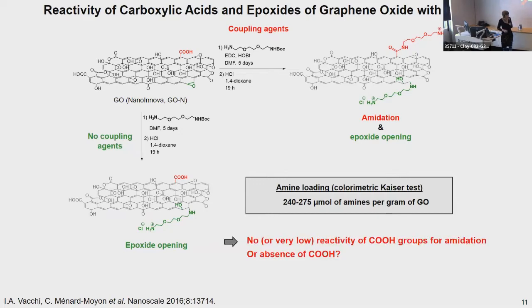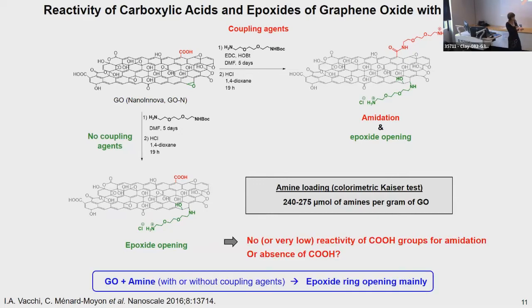So meaning that if ever there are carboxylic acid groups on the edges of the material, then they have a very low reactivity or no reactivity, or simply maybe that there are no carboxylic acids. So remember that when we mix graphene oxide with an amine, the main reaction occurring is the epoxide ring opening, with or without coupling agents.